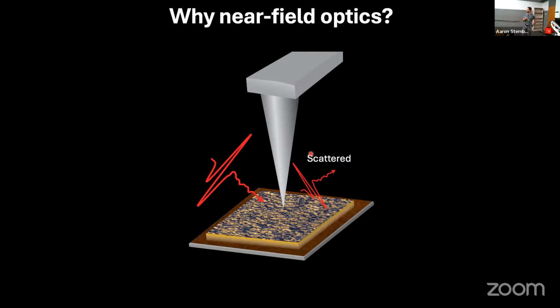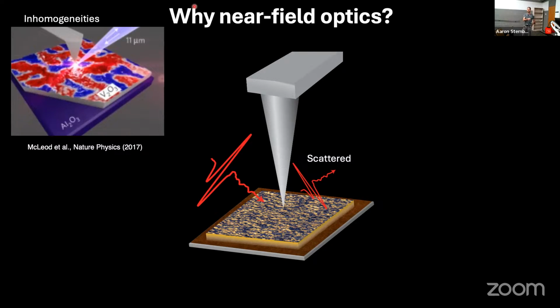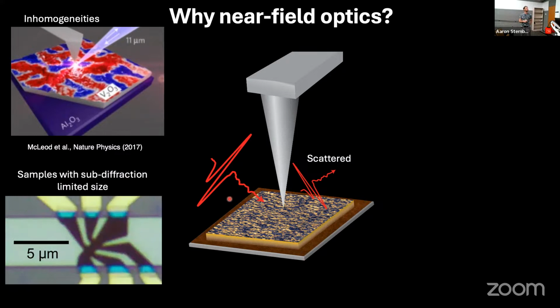So there's at least 4 good reasons to couple these techniques to AFM antenna, where you can get access to 10 nanometer spatial resolution independent of the wavelength of incident light. The first is that a lot of systems are naturally inhomogeneous. This includes phase transitions that develop inhomogeneously, as well as just imperfections. For example, in 2D materials, there's often wrinkles, bubbles, twist angle inhomogeneities, and so on. And these impact area average measurements, even though you are, in a sense, blind to them when the wavelength is too large.